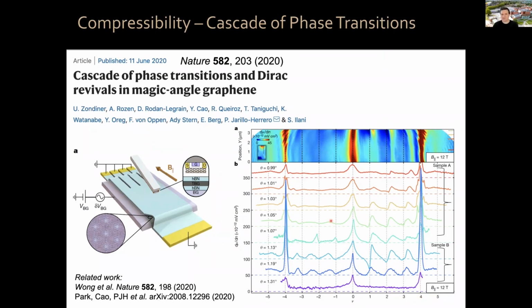If you measure the thermodynamic properties of the system, you measure the chemical potential, you measure the compressibility, you can see in this case, this is d mu dn, the variation of the chemical potential with charge density, which is the inverse compressibility. You can see that there is this sawtooth behavior, which occurs around each integer. And this should be interpreted as a cascade of phase transitions. So a phase transition is happening at each of these integers. And at each of these integers, what's happening is that the system decides to flavor polarize in some direction.